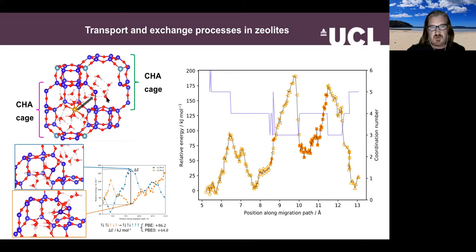So we've been using essentially simulated annealing, periodic DFT, and examining the barriers to migration within the, this is from one cage to another, so that's a rate limiting process. It turns out there's a lot of complexity here that you wouldn't perhaps have anticipated. This is really quite different from, say, alkanes within these materials.